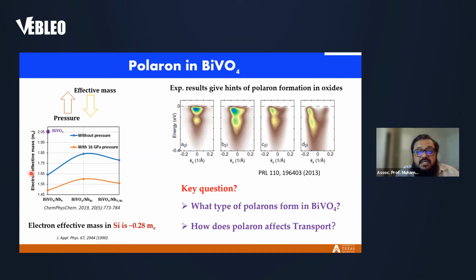The key question here, now these are experimental figures, just typical experimental figures that indicate the polaron formation below the conduction band. So the main question we are going to ask here is, what type of polaron forms in bismuth vanadate? Because we know from experiments that polarons form in bismuth vanadate, but we want to make sure that we understand what type of polaron, which is more dominant, and how they affect the transport.